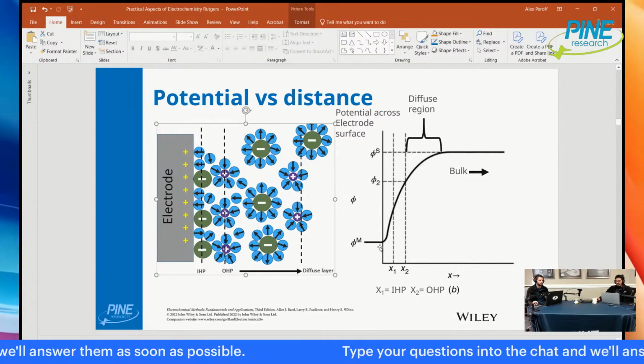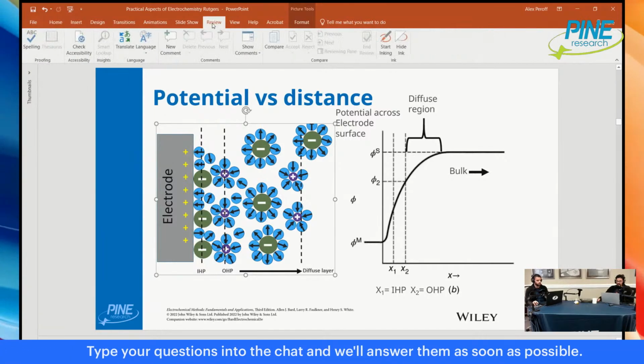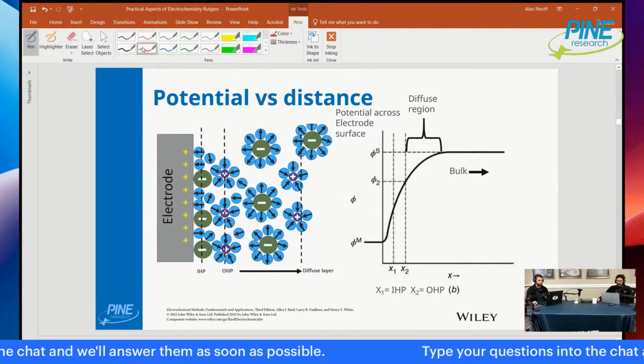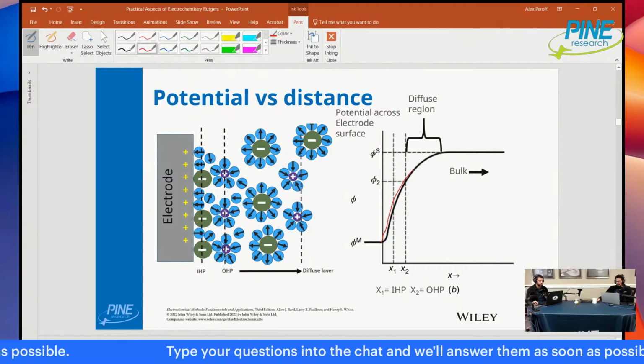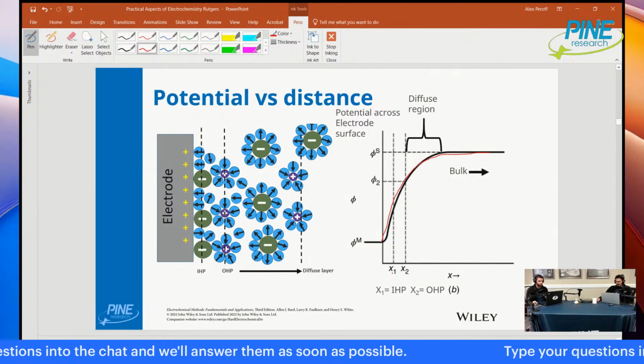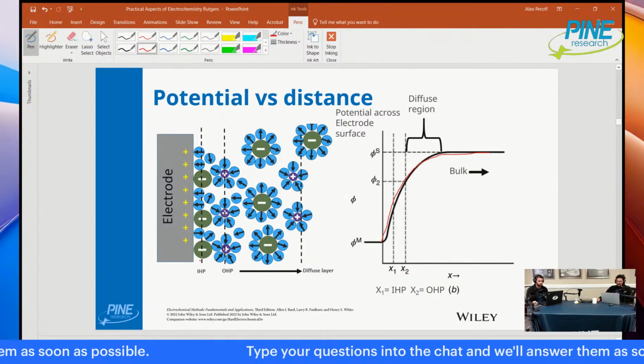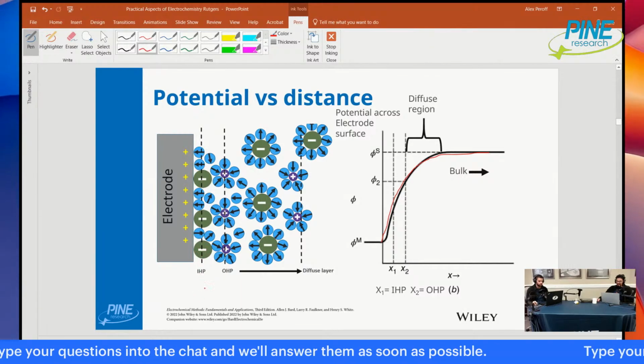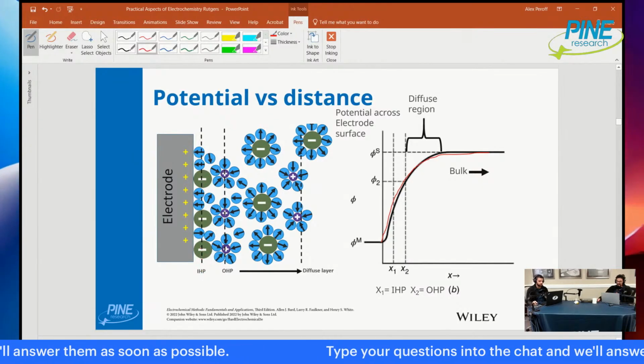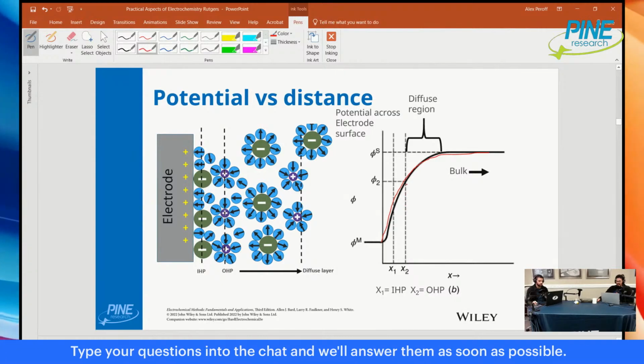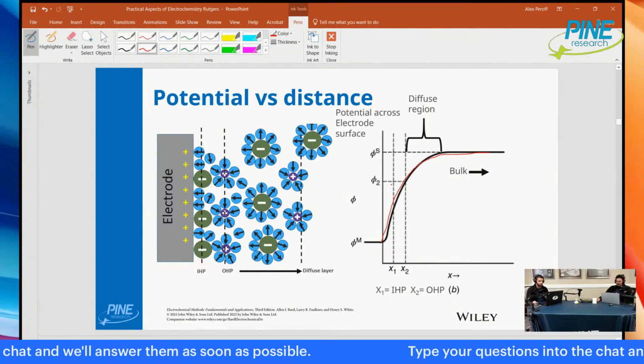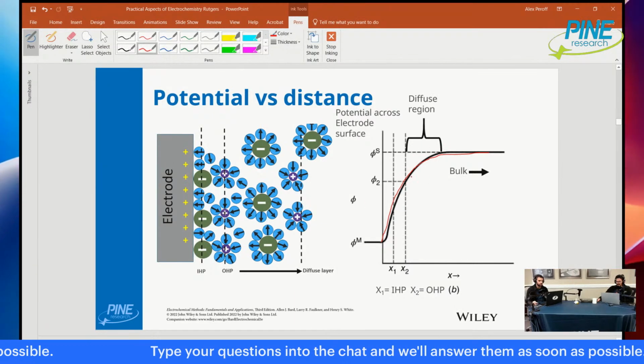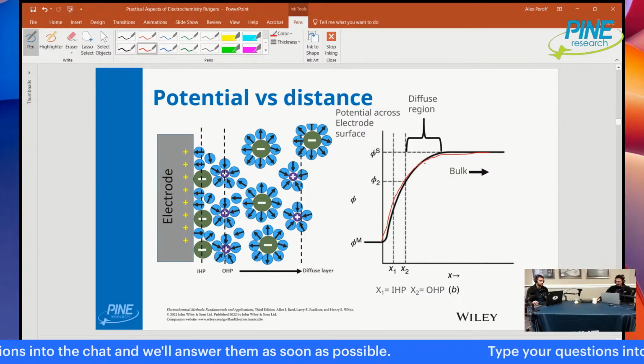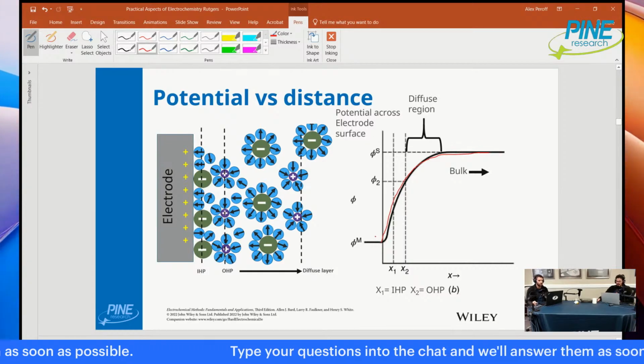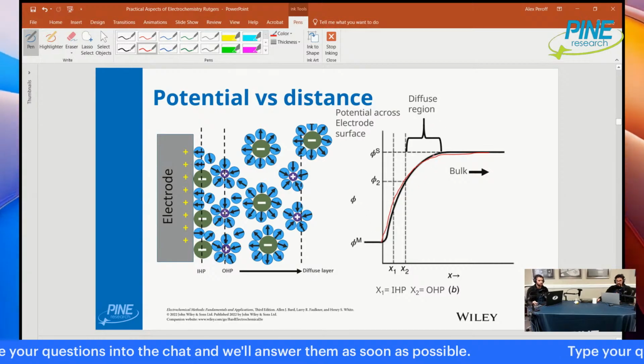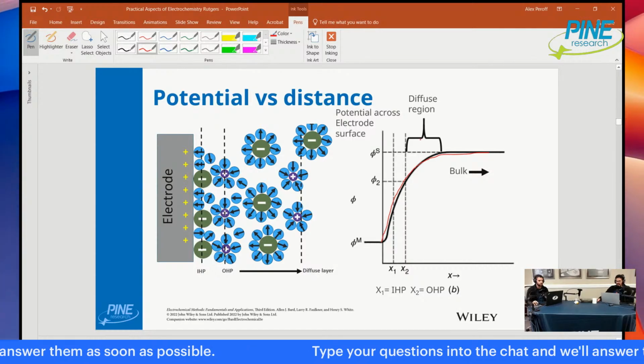When you have a supporting electrolyte of sufficiently high concentration, you see the potential drop off looks something like this. It goes from here all the way to here before it's basically the same. And X1 is the inner Helmholtz plane. That's like half an angstrom, right? It's from the center of an ion to the surface. So it's really, really short. Similarly, the outer Helmholtz plane is also not very far. And then there's this diffuse layer, which is not a well characterized zone, but you feel a field strength, and then it's as if you were in the bulk solution. So this change in potential is usually quite large, but the field strength is contained to a very small area.